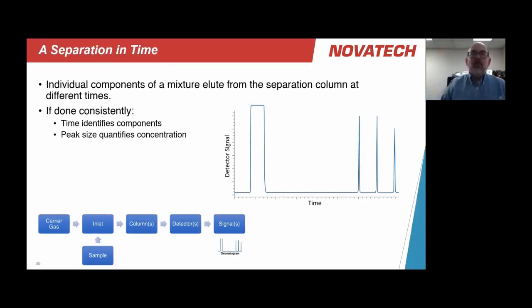We actually will take the sample and through a series of components within the analyzer itself, run it through separation columns so that we extract the components one at a time from the sample that we've injected into the analyzer. So there's a carrier gas that pushes along our little blob of sample that we've injected into it. As we go through the various columns, each of the individual components in the sample, or series of components sometimes, will come out of that column individually over time, which means that whatever detector we've got on the end here will see one component at a time.